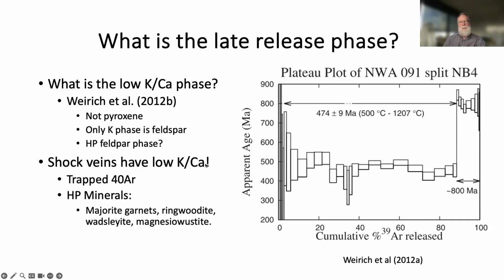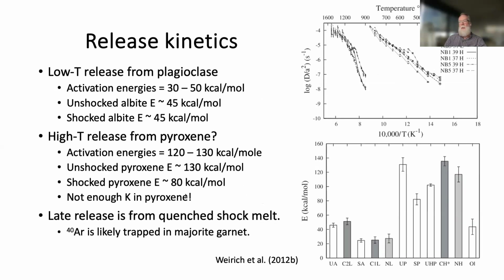The low potassium over calcium phase is the melt vein. And the high pressure minerals such as Majorite garnet are what have trapped the argon, but they don't have potassium in them. And so the late stage release must be from shock melt, and it doesn't represent an older impact event. It simply represents the retention of argon 40 in the high pressure minerals. This is consistent with release kinetics too.